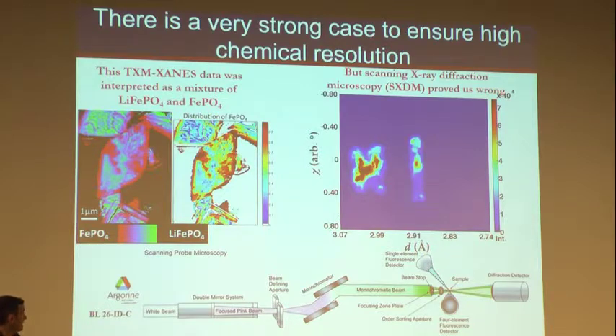Okay. And so depending on the 2 theta, because we know the system very well, we know exactly what lithium composition we have. There's plenty of data in the literature to compare. Given position of the 2 theta, given D spacing, that's the compound you have. And so if this is what this image is representing, that's the diffraction intensity for the whole particle. So these are all the individual mapping positions added together into a pattern that is the overall pattern of the particle. And so if you have 2 phases, you should have 2 peaks in 2 theta.